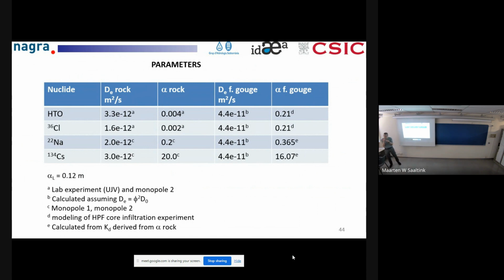Fault gouge is finely ground, very fine grained rock. During the movement of the fault, the granite has been crushed, so we have this very fine grained porous material filling the fracture. So this is filling the fractures to some extent, so I also take this fault gouge into account. Basically, you have larger porosity in the fault gouge and larger diffusion coefficient.